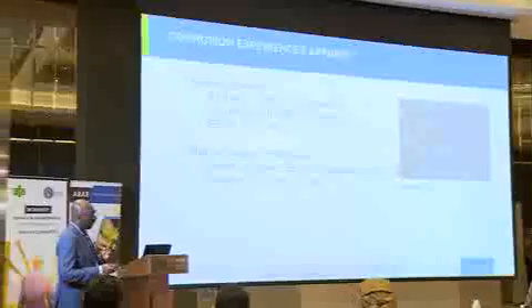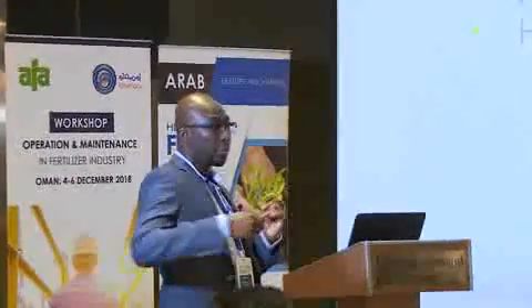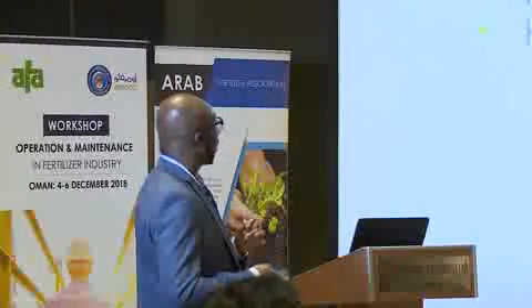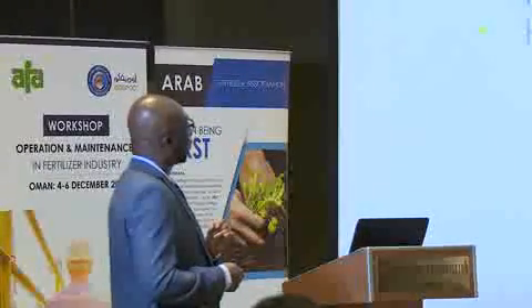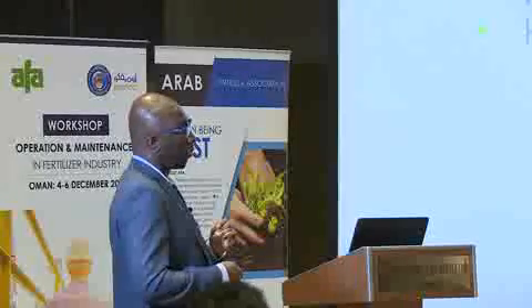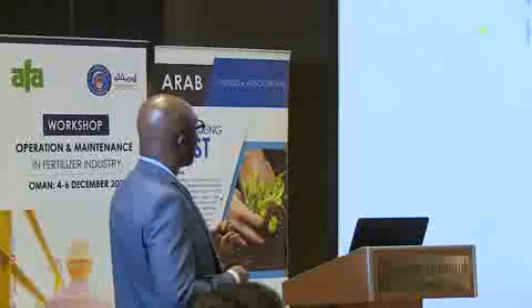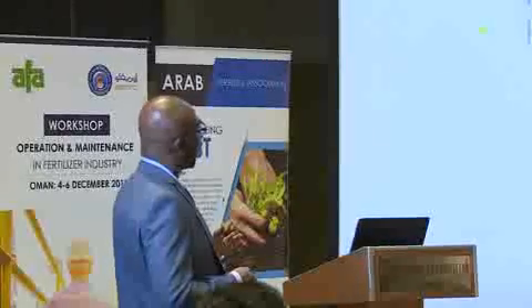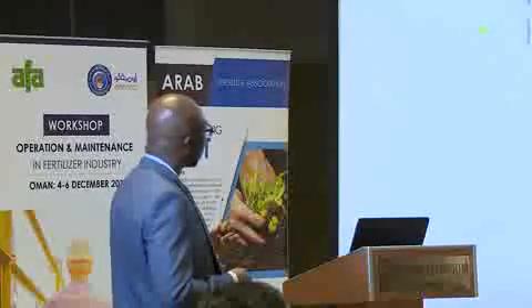So, let's come to this slide. After 20 years of operation, the main purposes for making Safurex have been achieved. We've eliminated quite a lot of the corrosion phenomena that are associated with austenitic stainless steels. And when we look at the plant, except for the stripper, we can see that for liner material, for example, the corrosion rate that we measure on Safurex is almost zero compared to the austenitic stainless steel materials, which are 316L urea grade and 25-22-2.